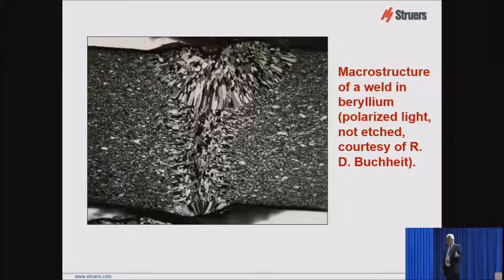technology used, either with the film or the... When you have an alloy like beryllium that is not face centered cubic or body centered cubic, that responds to polarized light like most HCP metals, if you use straight cross polarized light, you can see the grain structure beautifully. But if you add a sensitive tint filter, generally the image is wiped out.